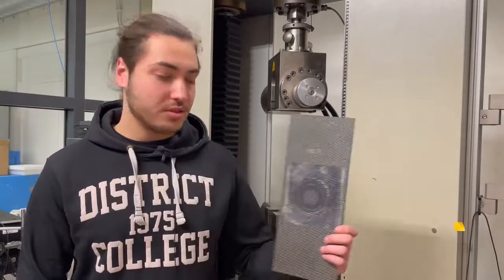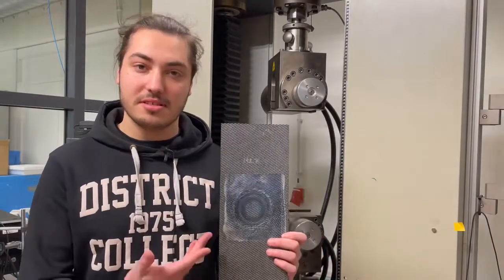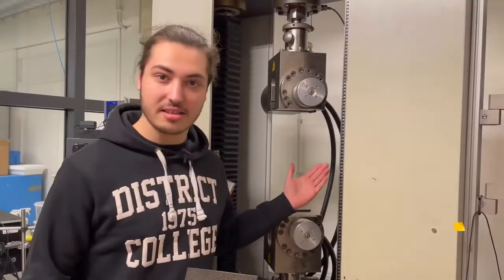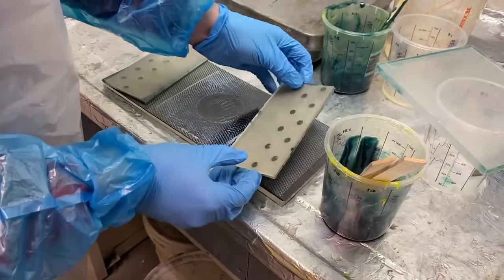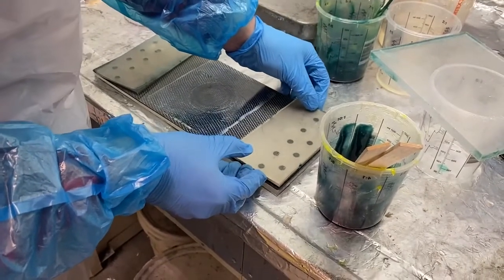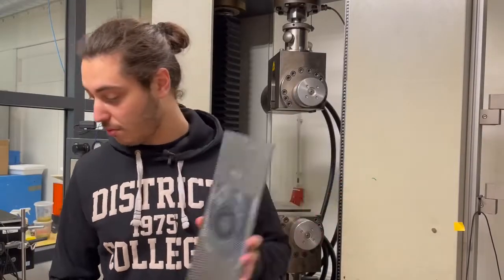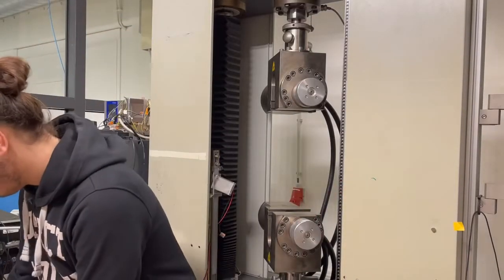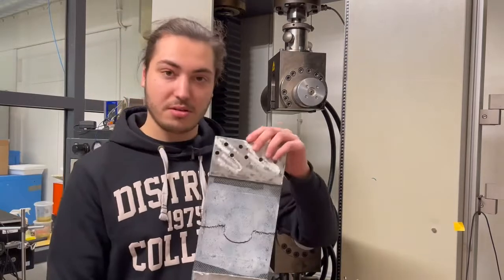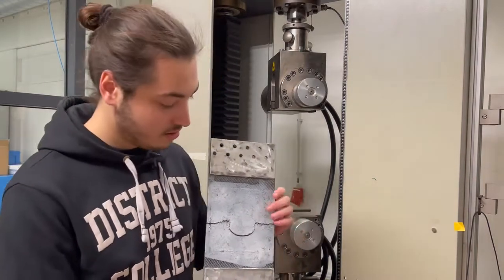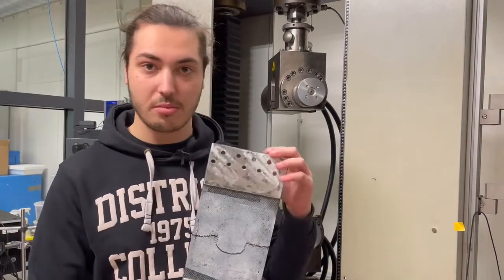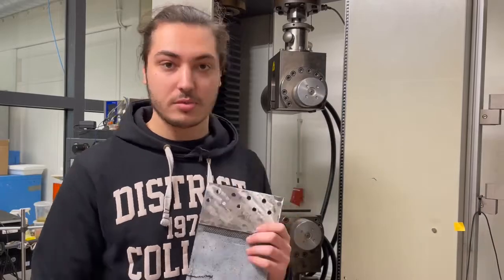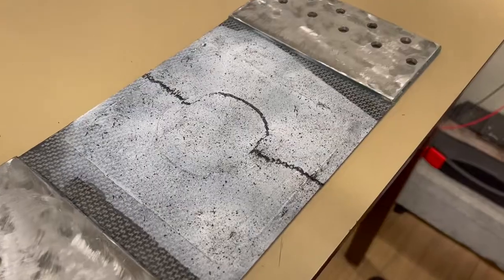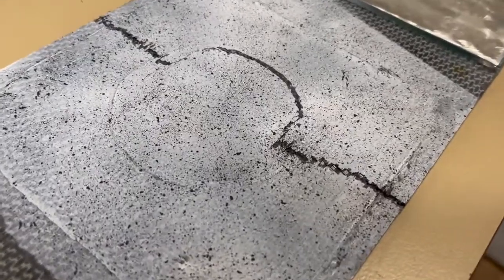Now, as you can see, the part has been repaired and cured. The next step was to validate the repair itself, and that was done with the tensile test. This is how the laminate was before being tested. And this is the aftermath. As you can see, it's painted white with some black dots. We used the camera for the digital image correlation, and you can see that it failed near the repair area.